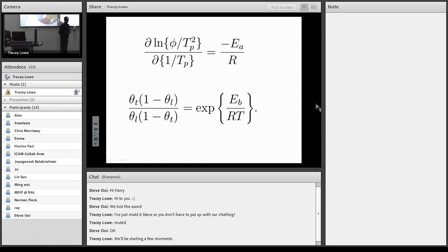Of course, Kissinger's original equation could be applied to any order of chemical reaction, but it is still a chemical reaction happening fairly homogeneously. So in this equation, this is the heating rate, and this is the peak temperature from your TDA curve. And from that, you get a binding energy. There's nothing in this about the shape or the size of the specimen. If I put a square specimen in TDA, I will get a different result from a cylindrical specimen. And the chemical reaction analogy simply isn't accurate because we get diffusion from inside to the outside.